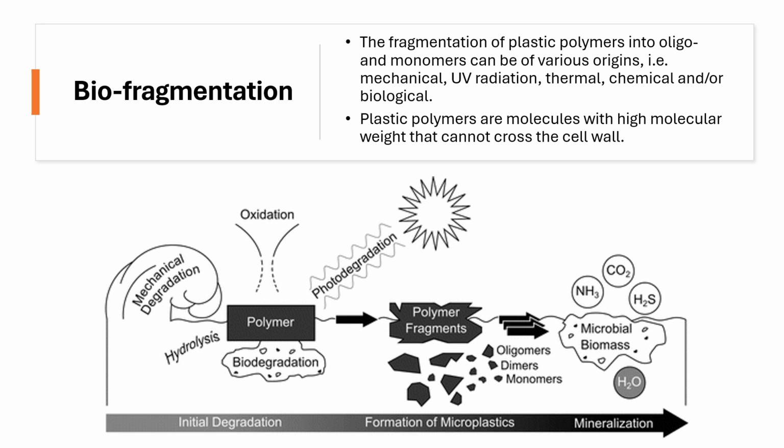For instance, monooxygenase and dioxygenase incorporate one and two oxygen atoms respectively, forming alcohol or peroxyl groups that are less recalcitrant for biodegradation. Other transformations are then catalyzed by lipase and esterase after the formation of carboxyl groups, or by endopeptidase for amide groups.